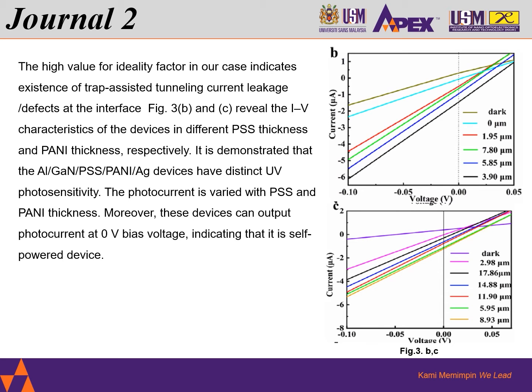Figure 3b and figure 3c reveal the IV characteristics of the devices in different PSS thickness and PANI thickness, respectively. It is demonstrated that the AlGaN, PSS, PANI, Ag devices have distinct UV photosensitivity. The photocurrent is varied with PSS and PANI thickness. Moreover, these devices can output photocurrent at 0 V bias voltage, indicating that it is a self-powered device.